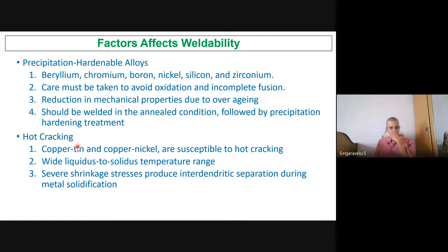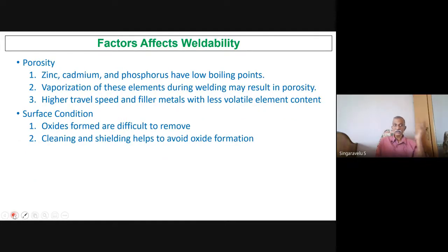Hot cracking is another problem associated with copper-tin alloys and copper-nickel, right? Because there is a wide difference between the solidus and liquidus temperatures. If you look at the iron-carbon diagram, something like that alloy system, the difference is very high, right? Severe shrinkage stresses are produced, right? Between the dendrites, the interdendritic liquid metal gets entrapped as a thin film, which calls for hot cracking, right? Porosity: zinc and cadmium have a low boiling point, which leads to porosity. Vaporization of these elements also results in porosity.